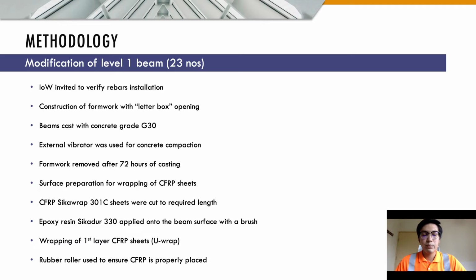Prior to the wrapping of CFRP sheets for the strengthening approach, a surface preparation process is required where all laitance and kinks were removed and the surfaces are ensured to be free from any dust. CFRP Sikawrap 301C sheets were cut to the required length according to the respective modified beam depth. Epoxy resin Sikadur 330 was applied onto the beam surface with a brush, followed by the wrapping of the first layer of CFRP sheets by U-wrap, which means the wrapping at the sides and the soffit of the beam. A rubber roller was used to ensure the CFRP sheets properly stick to the beam surface.